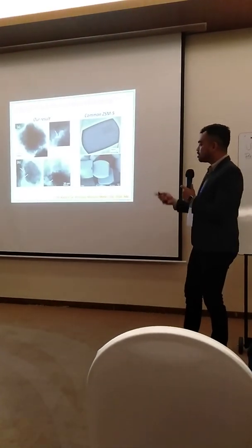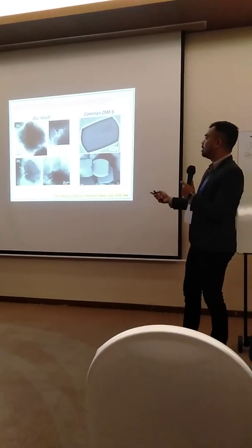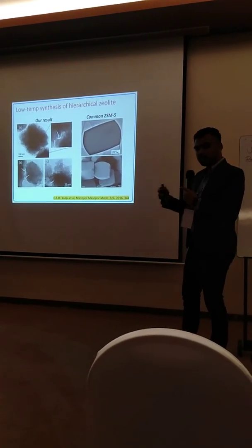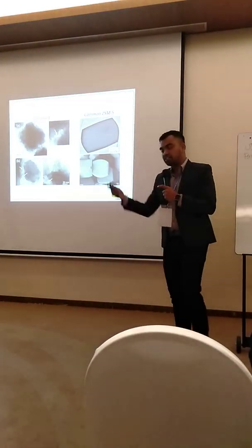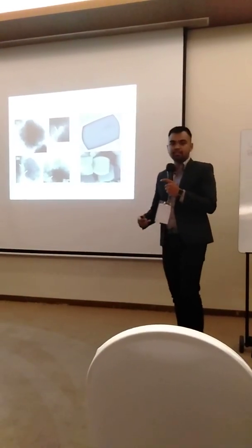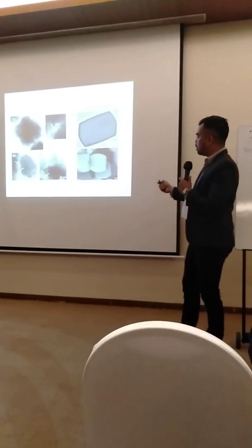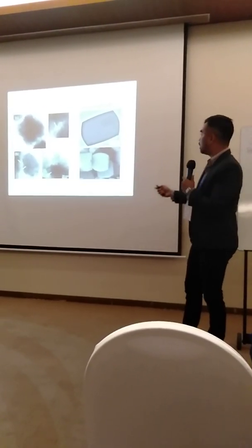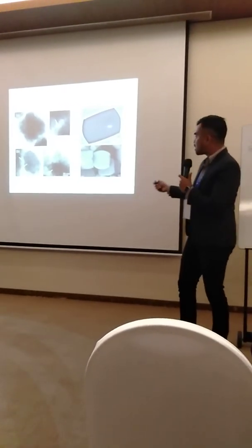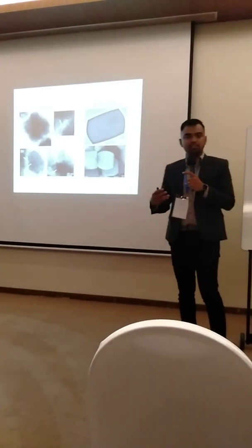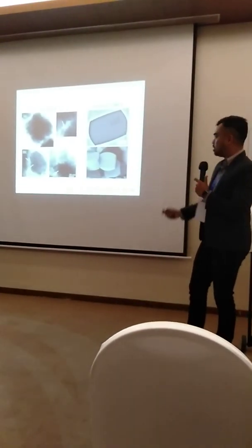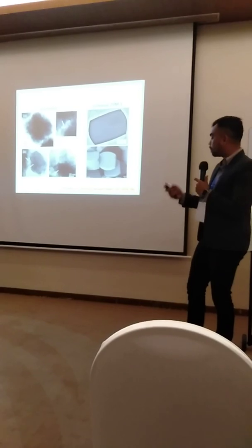But now we can synthesize the mesoporous zeolite, or sometimes we call it hierarchical zeolite, without the addition of additional organics. And you see, it is different from the conventional ZSM5, which has hexagonal prismatic morphology, or sometimes it is called coffin type, because it's like a coffin. This is purely microporous.